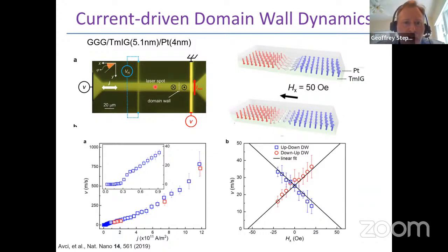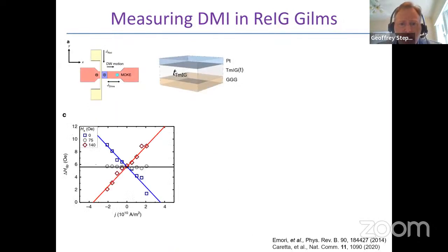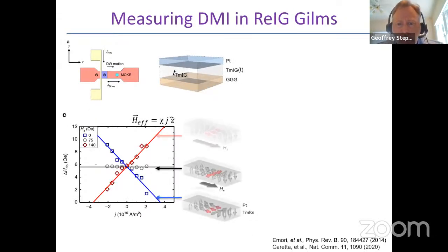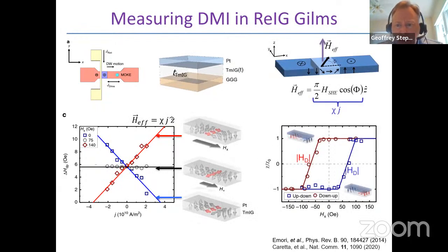We expected to be able to drive domain walls in these materials because we knew we could switch magnetization with spin orbit torques, but we didn't think that there would be DMI. And interestingly, there was. And so let me step through a couple of these because I don't want to go too far over.